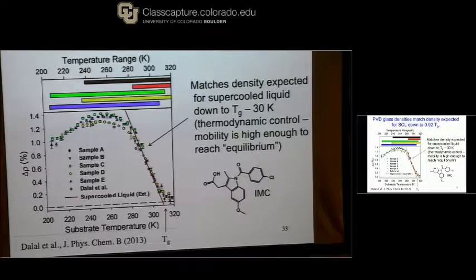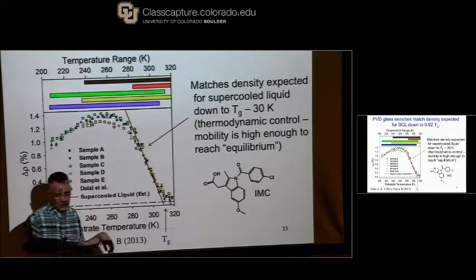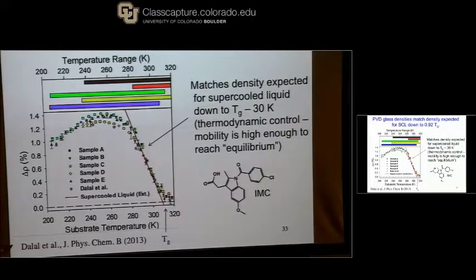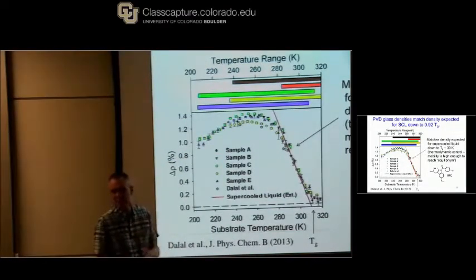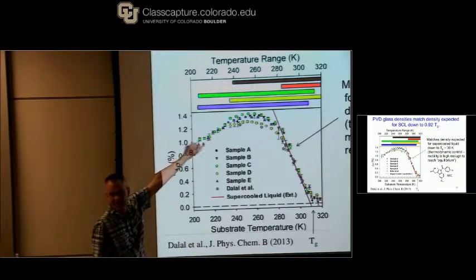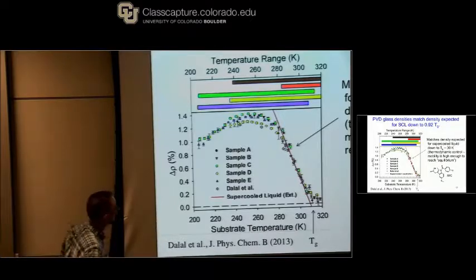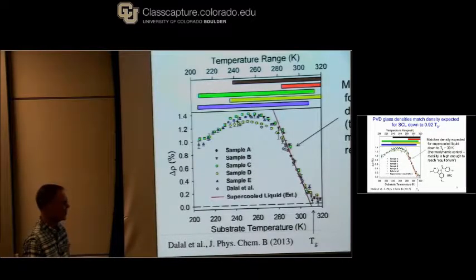So I'm going to interpret this plot as follows. What we have going on here is a competition between thermodynamics and kinetics. On this side, the kinetics are fast enough, the mobility is fast enough, that our materials reach the equilibrium density. So this is a region of thermodynamic control. Eventually, as I go down in temperature, I'm slowing down mobility at the surface, and I have to go into a regime where what can happen is limited by how much mobility I have at the surface. So this is a kinetically controlled regime. This is a tentative viewpoint at this point, and I'll show you more evidence that would support this.